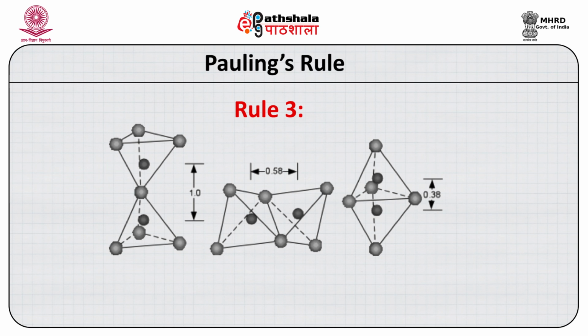For tetrahedral coordination in this figure, if the distance between the cations in the polyhedrons that share corners is taken as 1, then sharing edges reduces the distance to 0.58. Thus, sharing of faces reduces the distance further to 0.38.